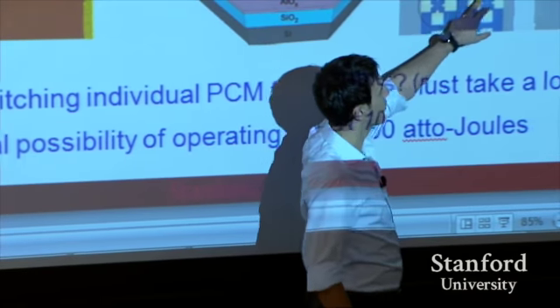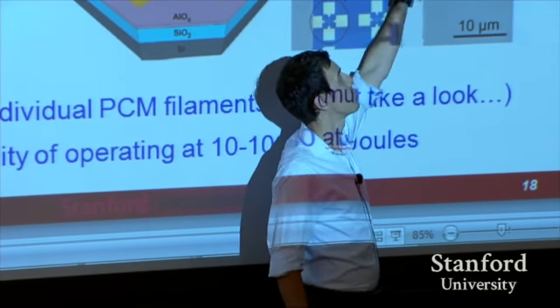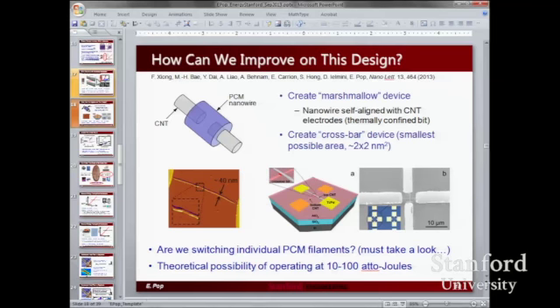How about manufacturability? How do you lay down 1 billion nano cups? Yeah, that's the $1 billion question too, right? A lot of my colleagues are struggling with this exact question, more for transistor and solar cell work than for memory. But it turns out that it is possible to grow almost perfectly aligned carbon nanotubes today. If you look at this picture right here, this is a cartoon, obviously, but this is a real picture, a scanning electron microscope image of 2 carbon nanotubes, which we were able to put perfectly at 90-degree angles. This was actually done by hand by a graduate student. What you can't really see in that picture is that there were actually a lot more nanotubes in there, but he etched them away. So it's possible to do this today.